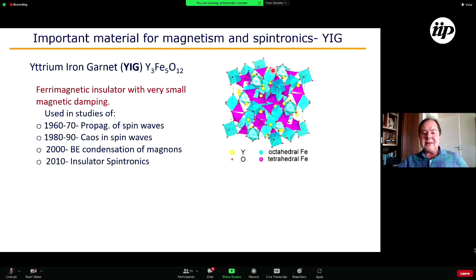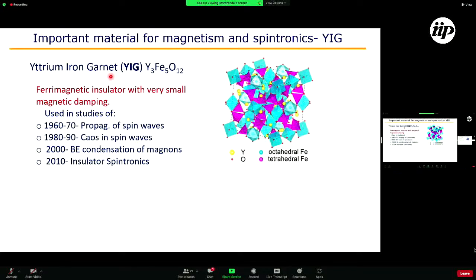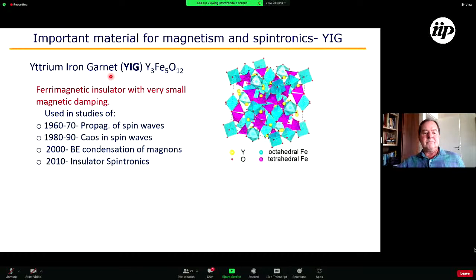And despite this very complicated unit cell structure, YIG has very small magnetic damping. In fact, it is the material with the smallest magnetic damping known until today. And this material is not found in nature. It was synthesized in 1956 or 57 by Bertaut and Forrat, two French physicists. And it was used in the 60s to study propagating spin waves.